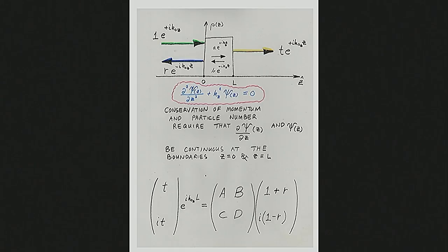Okay, so if you solve this equation exactly, we won't make that Born approximation, and we'll have, hopefully, a better representation of what the potential is actually doing to the neutron beam. Well, one way to solve this, because we can impose conditions that the wave function and its first derivative are conserved, are constant at each interface, which means that momentum and particle number are conserved. If I impose that condition, I can solve this problem in what's called piecewise continuous fashion and equate the wave function incident here outside the medium to that inside the medium, and the beam transmitted at this interface to that inside.